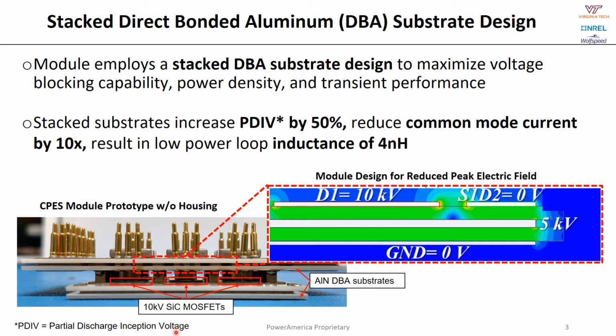The 10 kV module designed through CPES implements a stacked direct bonded aluminum (DBA) substrate design that allows us to harness all of the enhanced benefits of our 10 kilovolt wide bandgap silicon carbide devices. That includes increasing the PDIV, the partial discharge inception voltage, by 50%, reducing the common mode current in the module by tenfold, and resulting in a low power loop inductance of about 4 nanohenry. You can see that the substrates are stacked both on the top of the module and the bottom of the module to implement this geometry to harness all of those benefits and improve the performance of our power module overall.